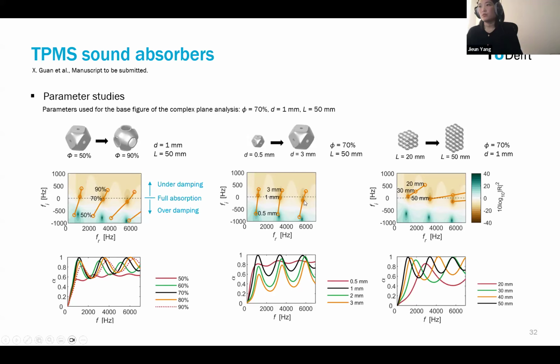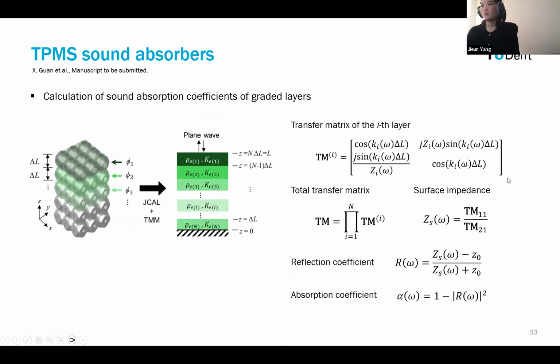For the 1 millimeter unit cell, you have these zeros close to these real axis values. So you have this high absorption coefficient at these peak frequencies. But if you are going away from this unit cell size, then you get lower absorption coefficient. And as we mentioned, our final goal was to obtain the optimal porosity distribution along the thickness.